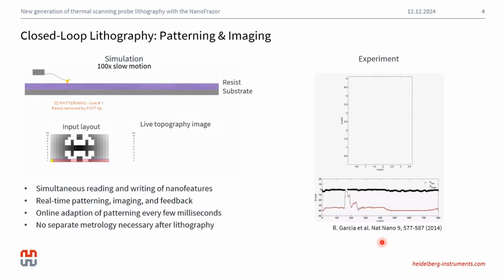And what is very important for the NanoFrazor principle is that we combine both the reading and the writing, and all of this is done in situ within the same system and with the same cantilever tip. So because of this, we say that we are performing patterning in a closed loop fashion. The way this works is exemplified in the simulated video. The cantilever with the heated tip moves in one direction to remove the resist according to your input layout and design. Then the tip cools down within microseconds to room temperature, and it reads the topography that we have just written. In the background, the software is comparing deviations from the intended design and the read topography, and differences of even a single nanometer can be detected and corrected for the patterning of the subsequent lines.